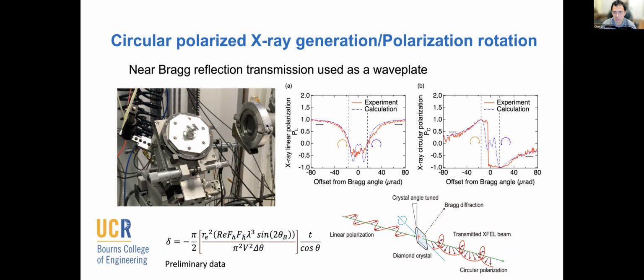At this transmission condition, the diamond crystal more or less works like a wave plate. So as you can imagine, if we change the angle of this wave plate, we should be able to tune this linearly polarized incoming X-ray beam, and we can make a circularly polarized beam, either left-hand or right-hand, or we can actually rotate the polarization vector. It turned out it's much harder than we expected.